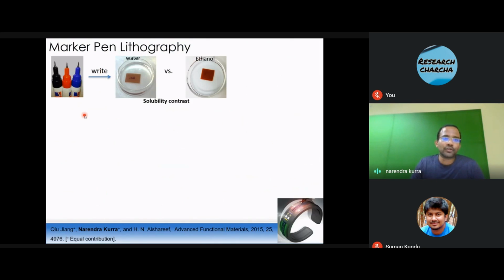Okay, not only photolithography techniques, we also developed some unconventional ways of making microsupercapacitors. I'm sure everyone must be using marker pens. The idea of a marker pen is that it should be stable against moisture. When you write something, it should not be erased under normal humid conditions. This is what we do: we take a marker pen and write on a plastic sheet, and when we dip it in water, you see the ink doesn't go off. Whereas when you dip it in ethanol, you see the ink erases off. There is a solubility contrast between water and the organic solvent.